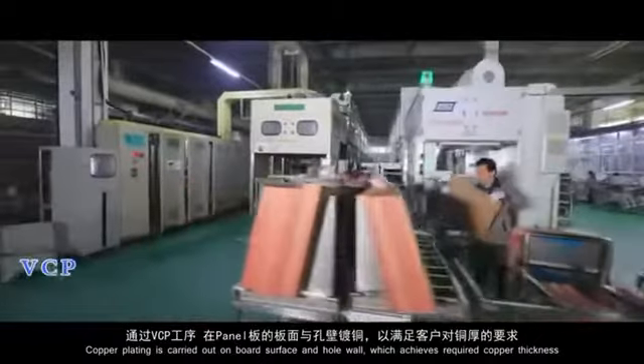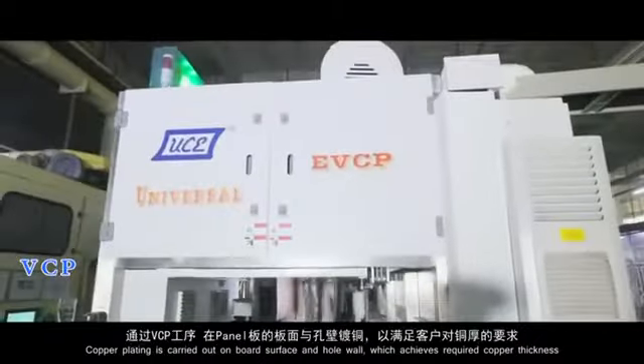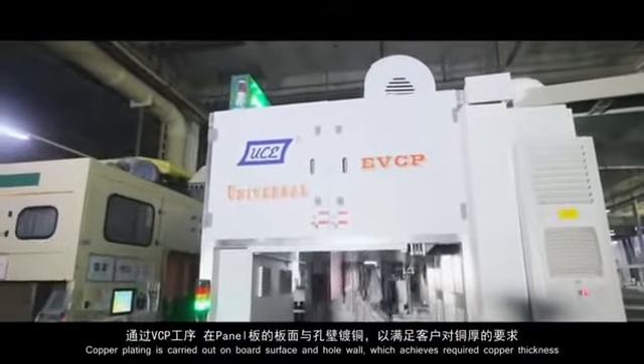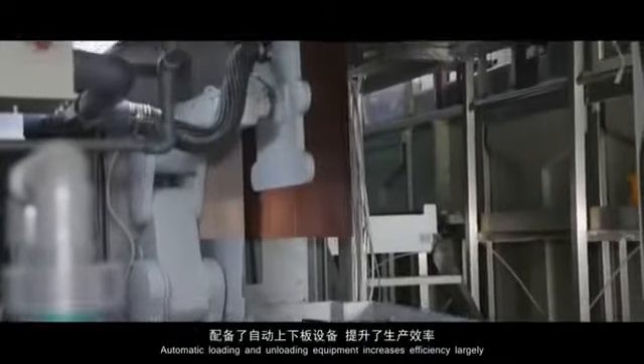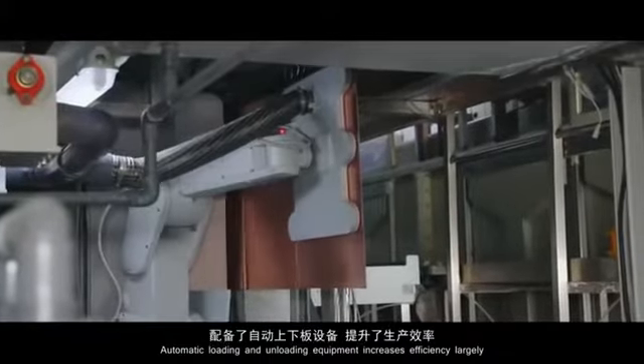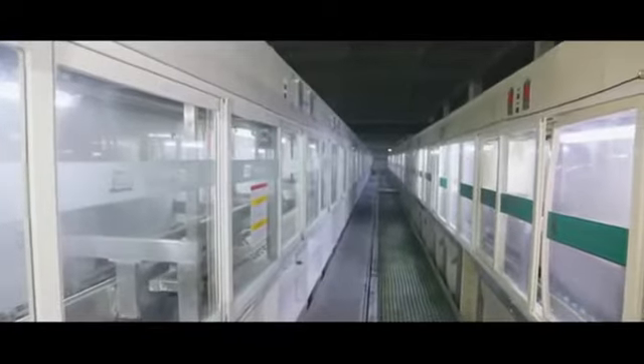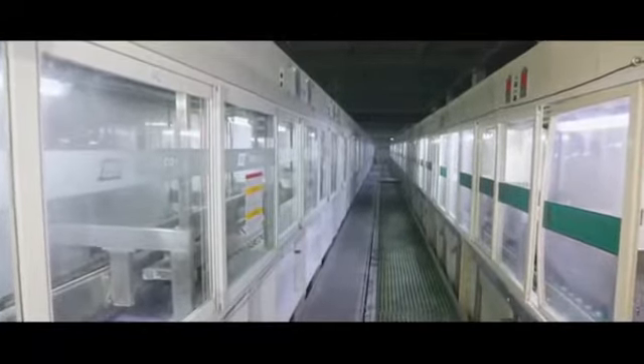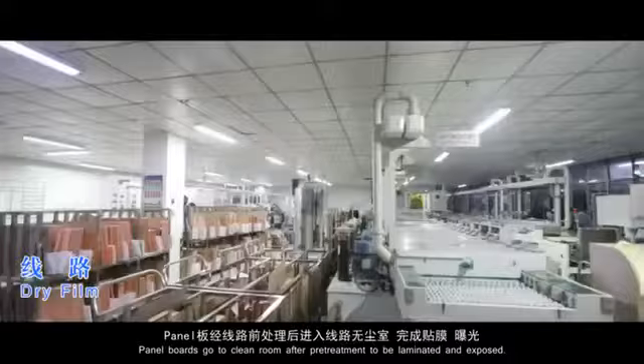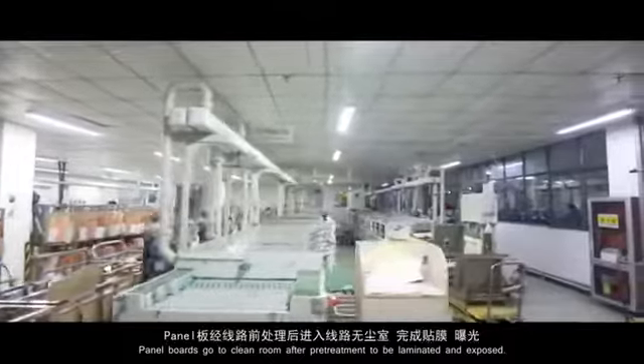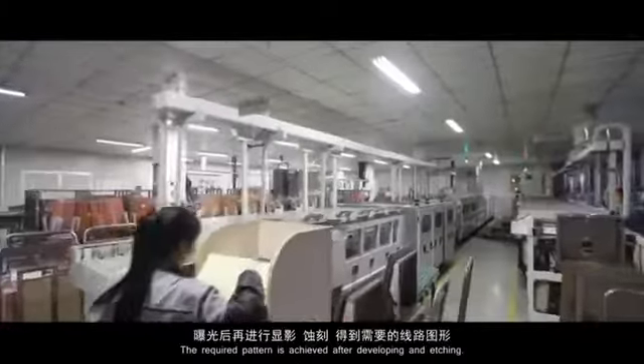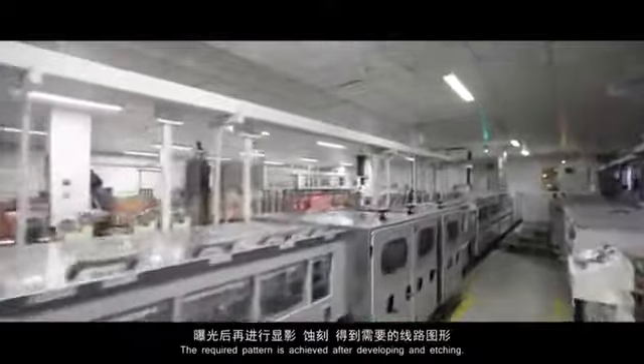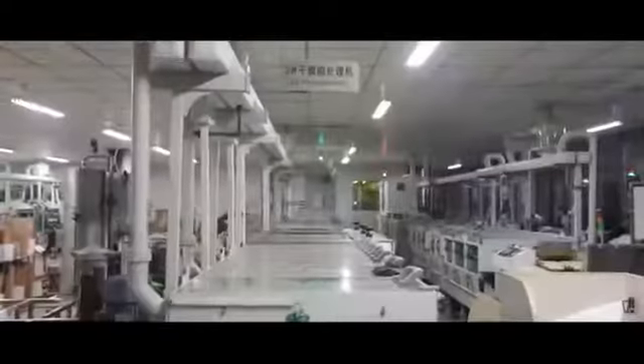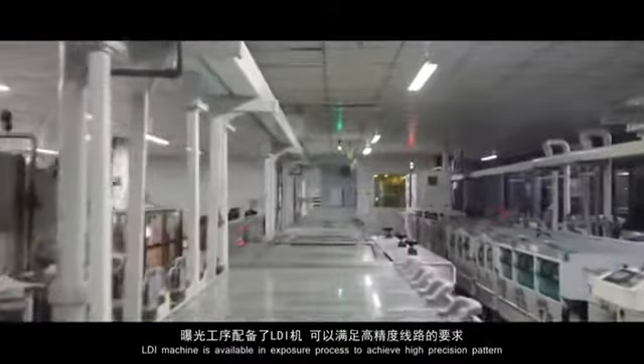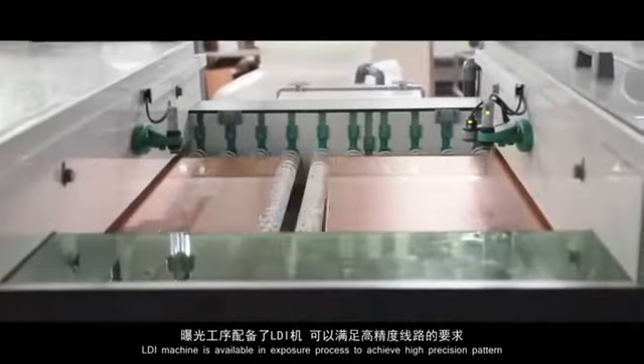Copper plating is carried out on the board surface and hole wall, which achieves the required copper thickness. Automatic loading and unloading equipment increases efficiency largely. Panel boards go to the clean room after pretreatment to be laminated and exposed. The required pattern is achieved after developing and etching. An LDI machine is available in the exposure process to achieve high precision patterns.